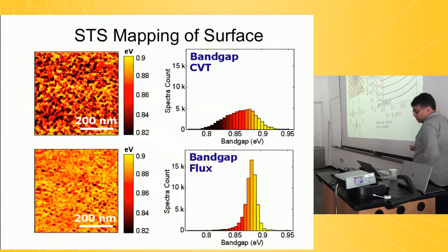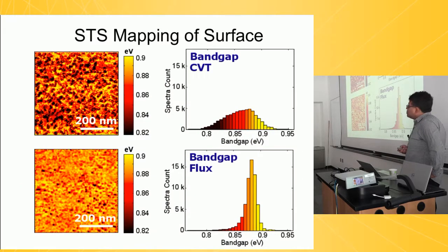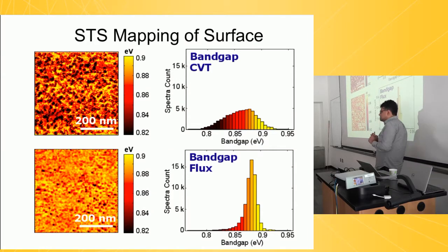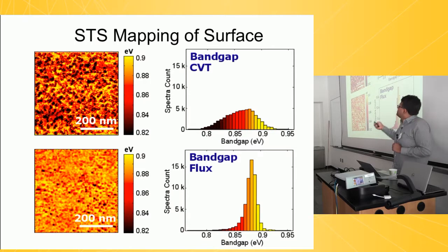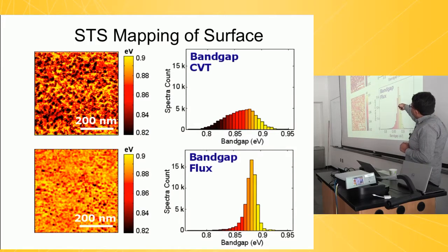Good. Now, what we can also do is go to every point in my crystal and measure the band gap that you see in STM. And in the vicinity of that defect, the band gap is slightly changed. What I'm showing here in the upper left-hand corner is a plot that measures what the band gap is at every point in space. And the size of this image is 500 nanometers.